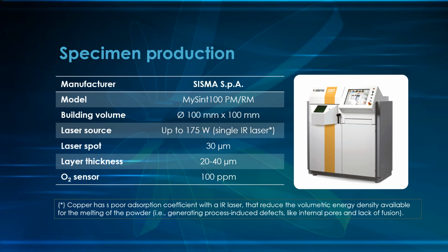In this work, specimens were produced by means of additive manufacturing, and in particular by means of selective laser melting, by using the instrument shown in the slide. So here you can see the machine characteristics, and one of the main problems in producing additive manufactured copper alloys is that those alloys are characterized by very high thermal conductivity and high reflectivity. Those two characteristics generate defects like, for example, cavities or lack of fusion that will affect the mechanical properties of the alloy.